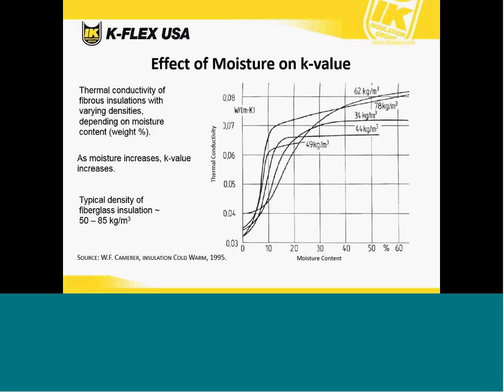I pointed out the K of water in the previous slide because it has a pretty profound effect on insulation. The value of K for water is about 16 times greater than your typical insulation K value, which means water is more of a conductor than an insulator. The thermal conductivity will increase as the moisture content of the insulation material increases. This chart shows the moisture content of a fibrous insulation and the resulting thermal conductivity as that moisture content increases. As moisture content increases, the K value increases fairly quickly. It's almost exponential, so you don't need a lot of moisture to degrade the performance of an insulating material.